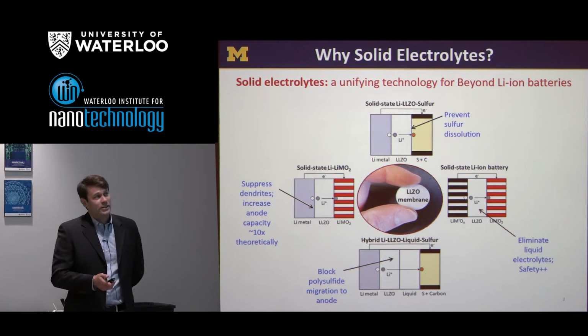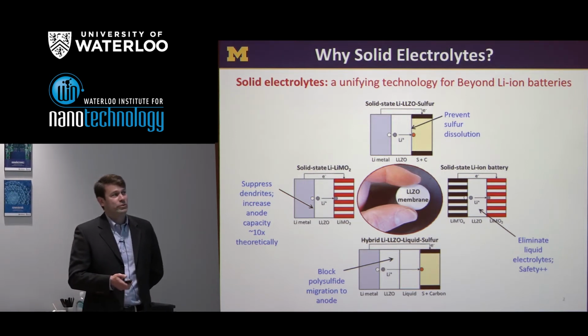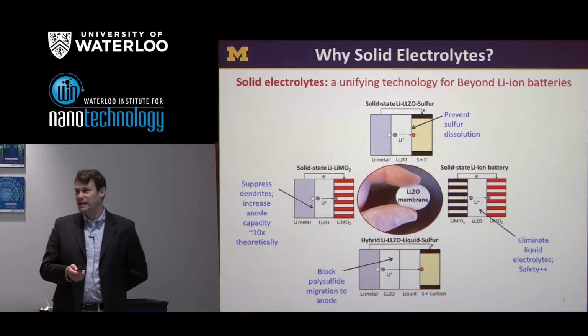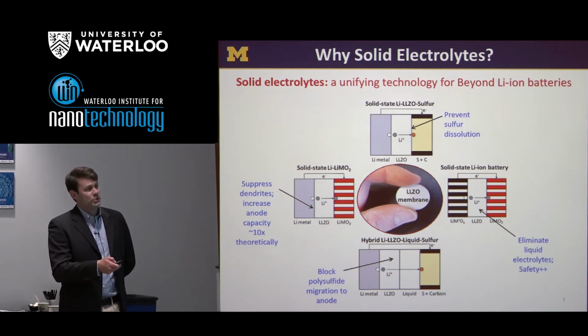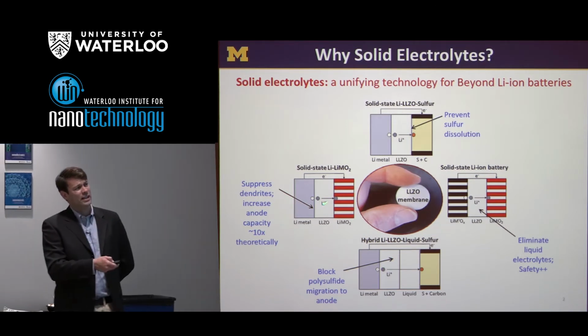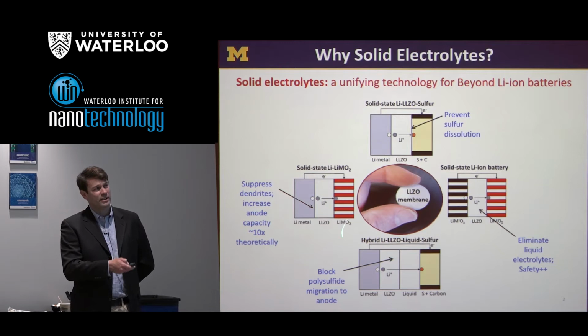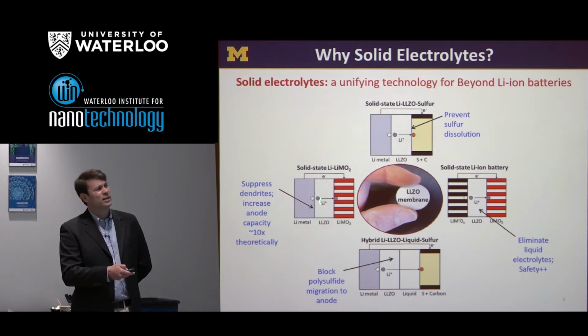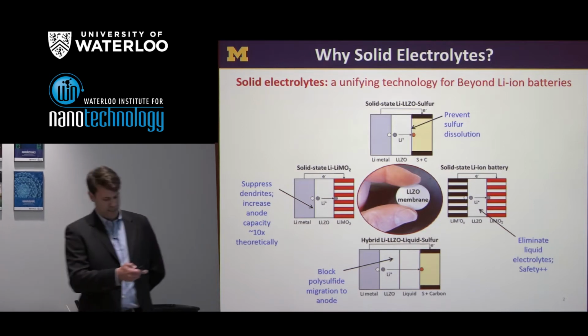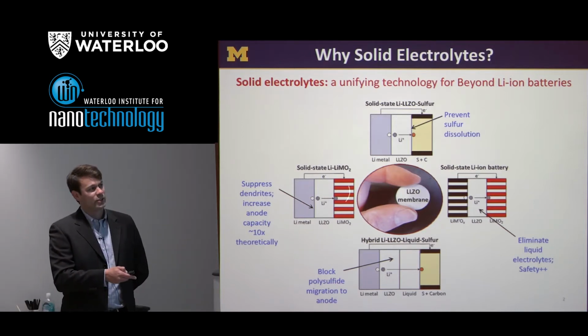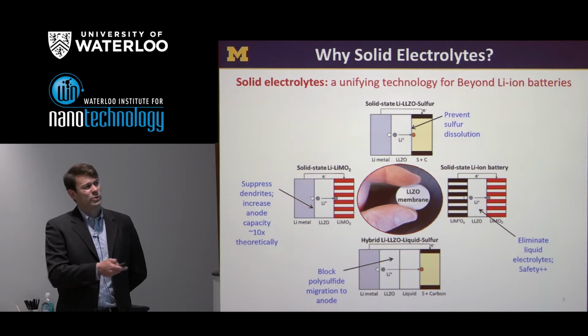So what does a solid electrolyte buy us? Well, it basically buys us two things. It buys us increased capacity and enhanced safety. So if we were to look at a normal lithium-ion battery, I'll use this cartoon here to the left. A normal lithium-ion battery has a transition metal oxide, an intercalation host as the cathode. On the negative side, or the anode, we would have intercalated graphite. And in between, we'd have a liquid electrolyte. And so our hope is that we'd be able to replace that liquid with something that's a solid.